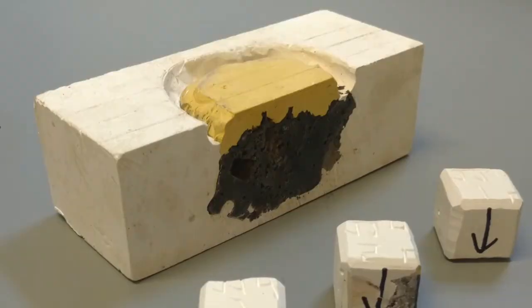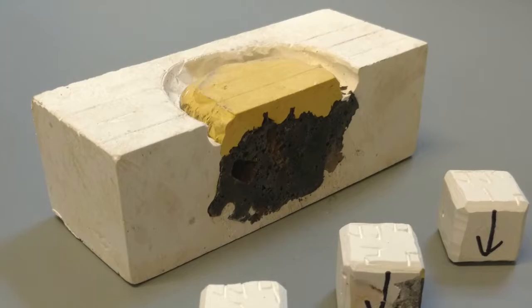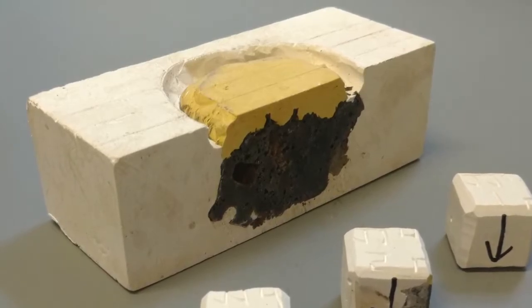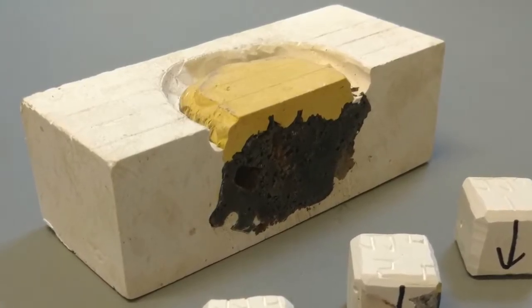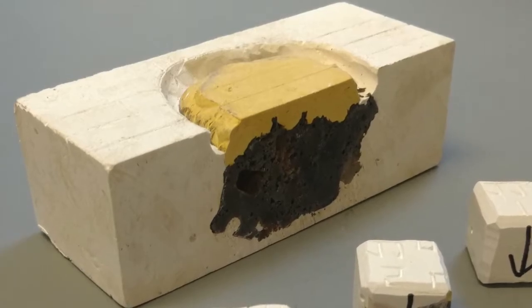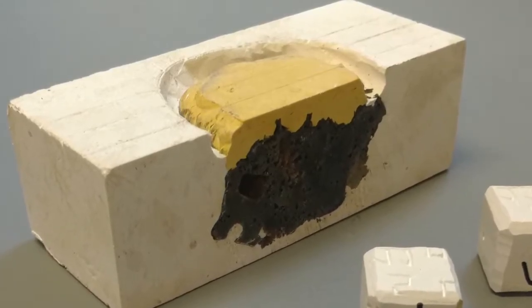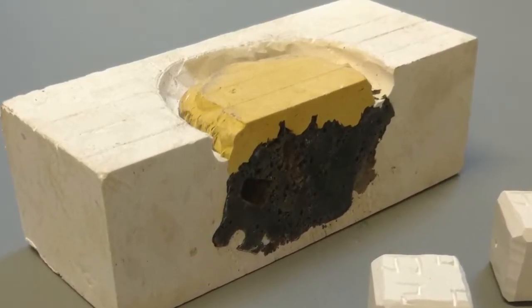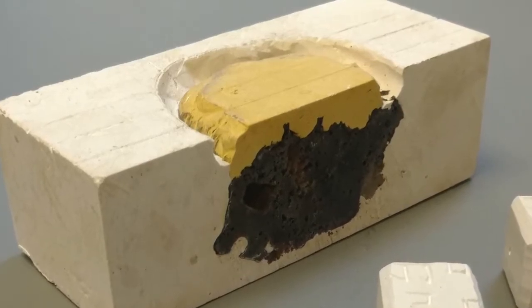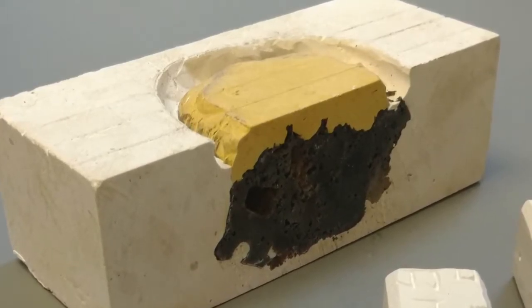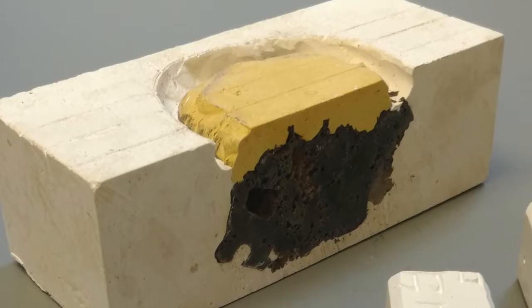In this project, we wanted to show that even though the magnetic signals in plaster are sufficiently weak to have little effect on the dating of some varieties of archaeological specimens with an already very strong magnetic signal, many other kinds of archaeological specimens can have signals so weak that we may be measuring more plaster than specimen, and this is likely severely confounding results in some cases.